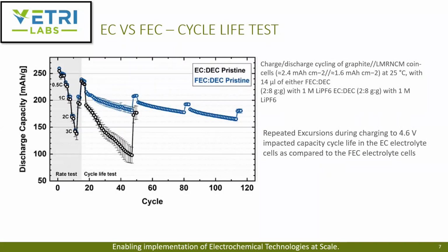This is discharge capacity in milliamp hours per gram of the material, versus cycle. You can see this is done at 25C. You can kind of see the rate test and the cycle test, and there were repeated excursions during charging that go up to 4.6 volts. Again, it only sees 4.7 volts one time, and then the rate test and cycle life test go only up to 4.6 volts.